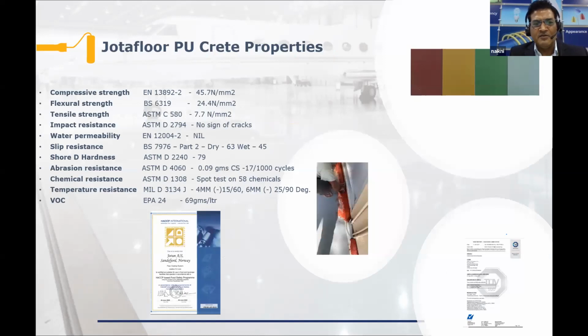It has a number of unique features: compressive, flexural, tensile, impact, water permeability, slip resistance, shore hardness, abrasion, chemical resistance, temperature resistance, and its volatile organic compound is only 69 grams. That means anything below 100 is low VOC compliant.